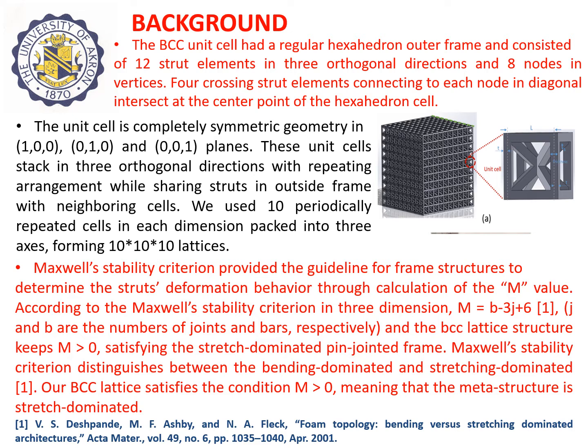The BCC lattice structure keeps M larger than 0, satisfying the stretch-dominated pin-jointed frame. Maxwell's stability criterion distinguishes between the bending-dominated and stretch-dominated cases. Our BCC lattice satisfies the condition M larger than 0, meaning that the metastructure is stretch-dominated.